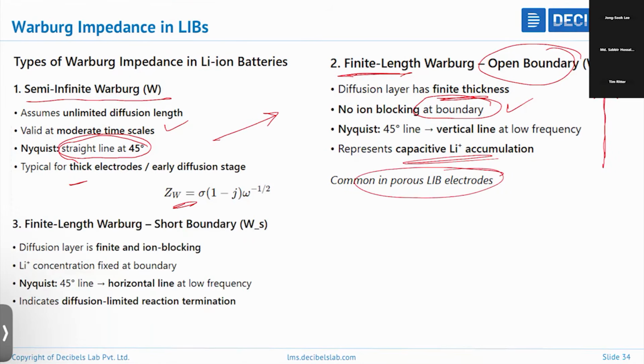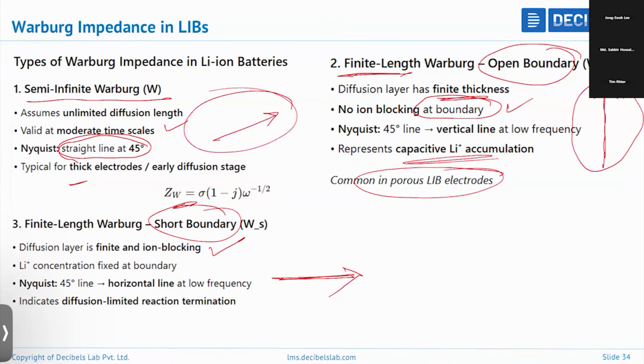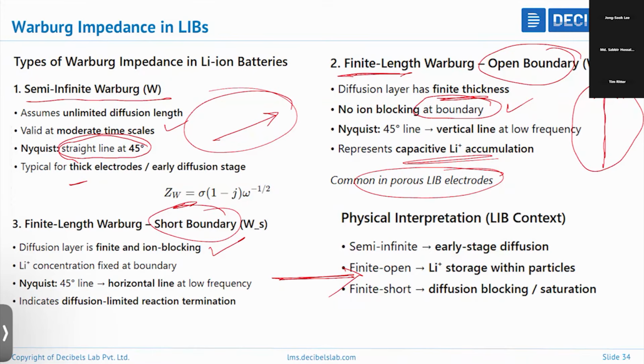And the third type is the finite length Warburg with short boundary. The boundary is short, so this represents the ion blocking. So the lithium ion concentration is fixed at the boundary. In this case, that line at lower frequency will be parallel to the x-axis. So generally we get this. If you are getting that line at lower frequency parallel to the y-axis, then it is because of finite length Warburg, open boundary, WO, and if it is short boundary, we get that line parallel to the x-axis. So overall, the three types of Warburg are semi-infinite,